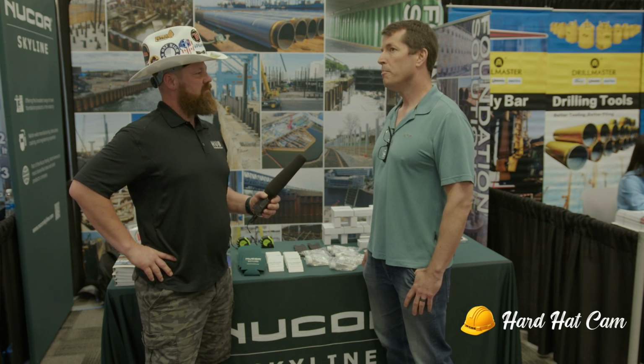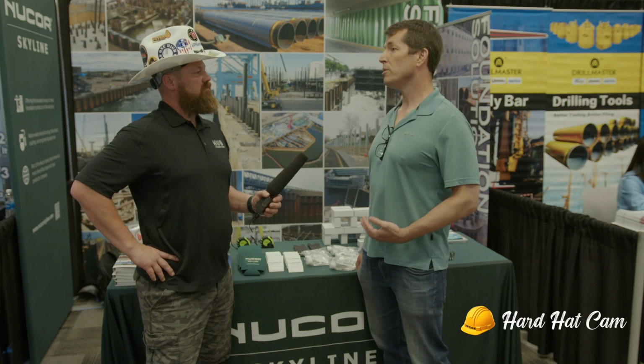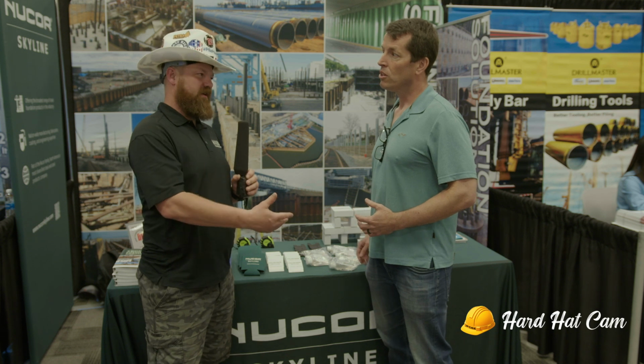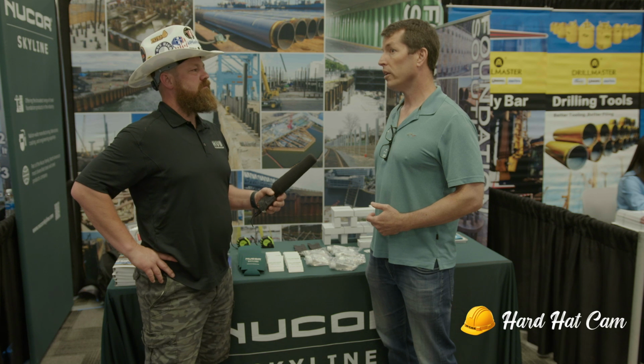I think the big difference between our position on corrosion and what we see in the industry is that a lot of engineers will design a steel section and then think, I have to add protection to the steel. So they add coating, or they galvanize it, or they make it thicker, after they've done the design. Our position is that the durability of that section, or the corrosion, should be part of the design. And so you're referring to sacrificial steel? Sacrificial steel, but possibly steel grade, or the chemistry of the steel.